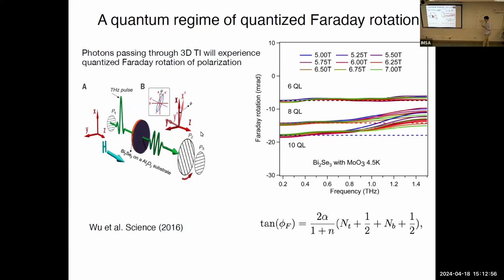the theoretical expectation that in TIs, if you probe it with suitable frequency and you don't have too much disorder in your sample, you can actually see the quantized effect not only with electric probes, as it's done in Hall transport, but also with optics. So, also fun fact, turns out some insects have vision which is sensitive to the polarization of light. So if you were that insect, you would actually be able to see this effect of quantum Hall effect with your eyes. But yeah, unfortunately, we don't have that. But yeah, in theory, you could.